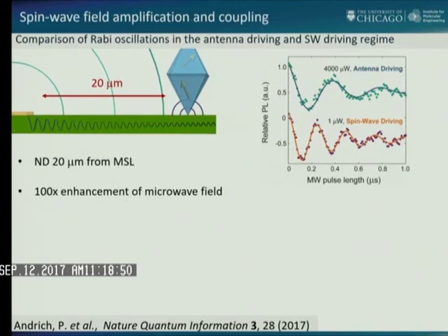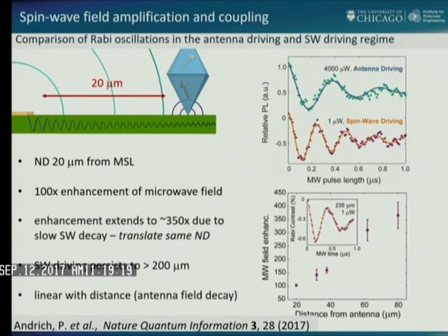The really interesting thing is that it enables you to communicate between quantum states over much bigger distances than people thought. So just to point out again, this is 4 milliwatts in conventional driving. This is 1 microwatt using a spin wave. Same particle, same place. And if you look at the amplitude of the signal, it's 100 times stronger using the magnet. So what he did then is take this little membrane, pick it up, move it farther and farther and farther downstream to see how this worked.